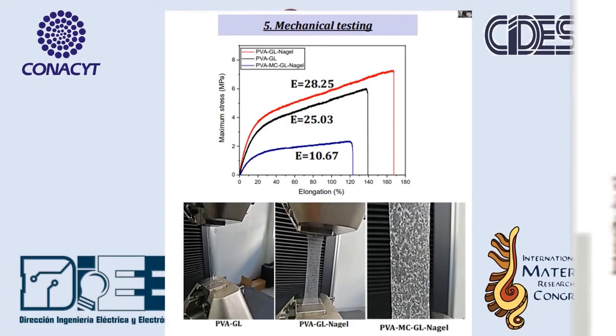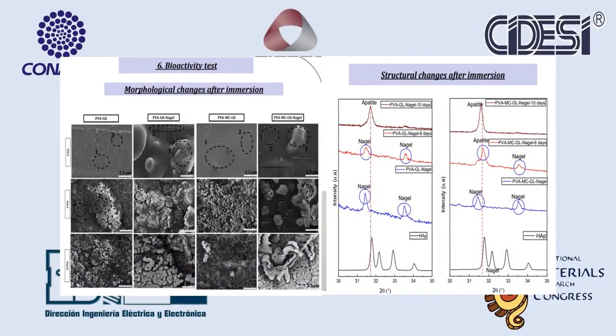Mechanical tests show that the polyvinyl alcohol membranes with glycerol, with and without Nagelschmidtite particles, have very good mechanical properties, especially elongation above 100%, which is favorable for the placement of the dressing as they are flexible and can be adapted to different wound areas. The bioactivity test shows that the membranes are able to promote biomineralization mechanisms.